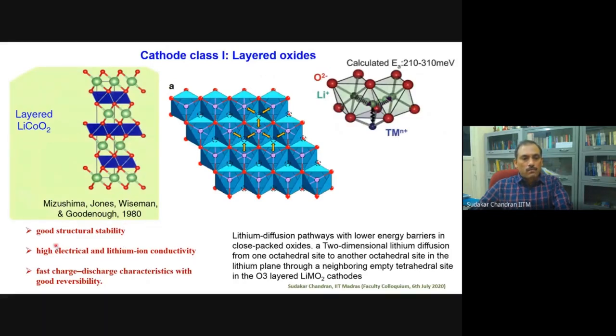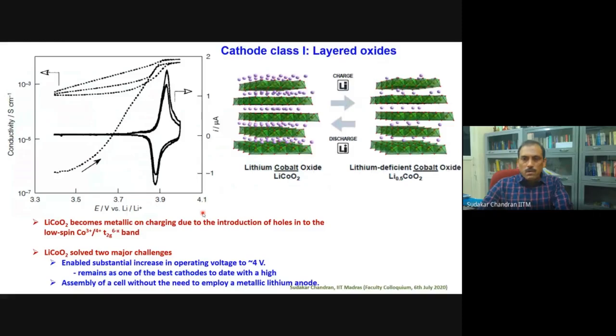So they had a good structural stability. They had a good electrical conductivity. The ionic conductivity was good. Therefore, fast charging and discharging characteristics was possible. In fact, the lithium goes from one octahedra to other octahedra through the tetrahedral sites, which lie in between. And the typical energy required is about 0.2 to 0.3 eV. So this was like a wonderful material that John Goodenough came up with. And it solved two major problems.